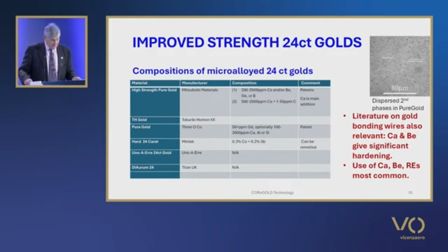The age-hardenable alloy is of 995 fineness and contains 0.2% cobalt and 0.3% antimony. It is based on precipitation hardening by a gold antimony intermetallic, AuSb2, with the cobalt retarding recrystallization. The gold antimony phase diagram is a eutectic system at the gold-rich end and shows similar features to those I showed earlier.